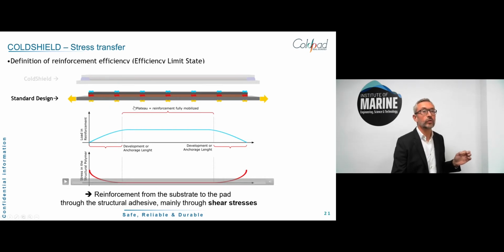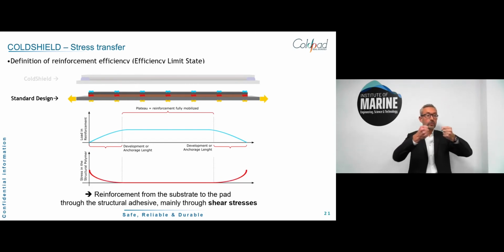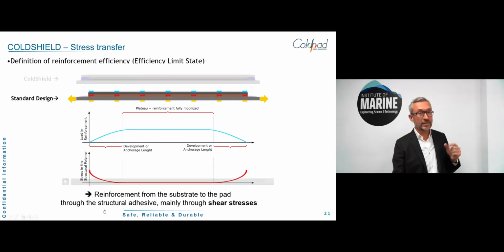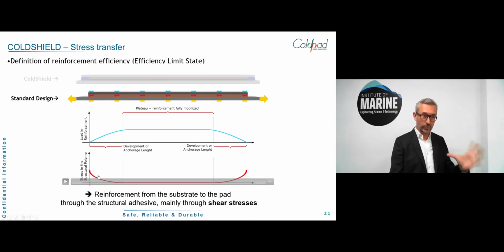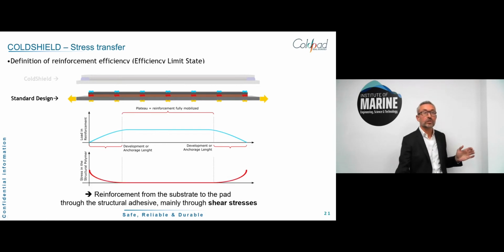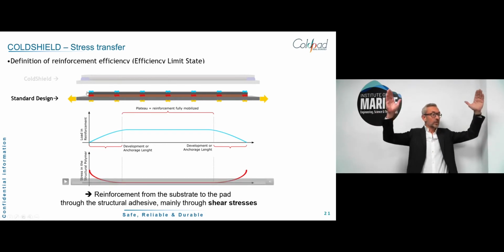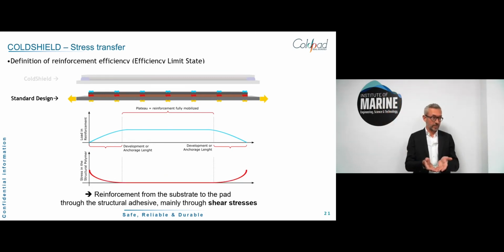So all the force will go here, and so it will take time to have the reinforcing plate fully loaded, okay? And when the plate is fully loaded, it's acting like two springs in parallel. It will deform the same way. Meaning that the stress will be transferred mainly during this anchorage length. And this is where it gets tricky for bonded reinforcement, or actually for bonded assemblies, to transfer easily the stress from the base metal to the reinforcement in this short area. And what happens is, because of the geometry, you have a discontinuity, and this is explaining the bathtub profile of the stresses, right? So meaning that if you do a finite element analysis of this area and you refine the mesh, the finer the mesh will be, the higher the stress will be. Okay, because basically you're converging towards the analytical solution, which is infinite stress.